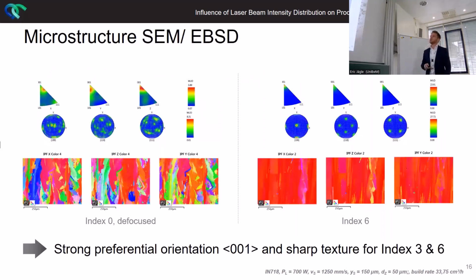So we dive deeper into the texture analysis via EBSD. And what you can see here on the left side is that the grain orientation for the sample of index 0 is quite irregular, while there is a strong, sharp, preferential orientation along 0, 0, 1 for the samples of index 3 and index 6. But then naturally the question came up, why is that pronounced for the different intensity distributions?